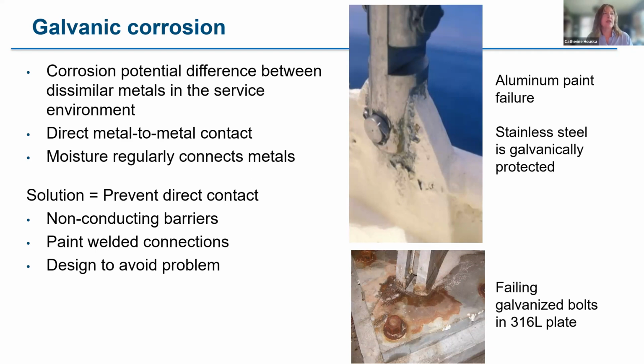But what you can do is use a non-conducting barrier. There are a variety of different polymer materials that are used between metals to seal them. The appropriate choice will really depend on likely movement, temperature, and a whole variety of other factors. You can paint joints that are welded to each other. So if you have stainless steel welded to carbon steel, paint the joint, at least 2 inches out from the joint. And then someone needs to inspect it to make sure that you maintain a paint barrier to prevent galvanic corrosion.